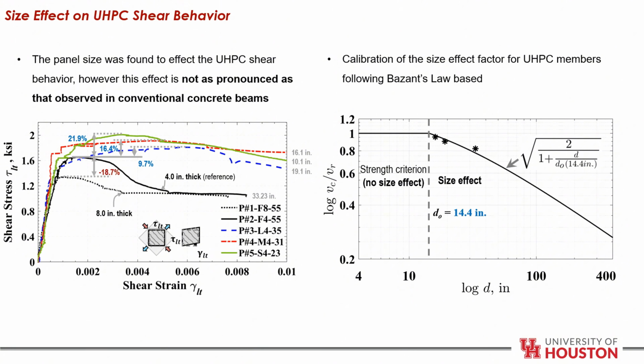On the other hand, the depth of the panel also influenced the shear strength of UHPC panels. As we can see here, doubling the thickness decreased the shear strength by 18%, while decreasing the depth increased the shear strength by 10% to 22%. The results from the panel tests under the size effect study were utilized to calibrate the size effect factor, and it was found that the characteristic depth of 14.4 was adopted, beyond which the size effect is significant and needs to be considered in design.